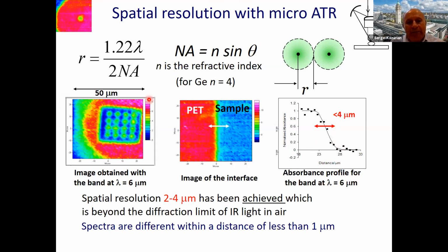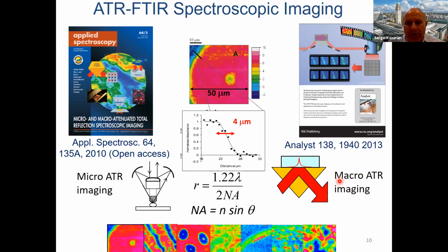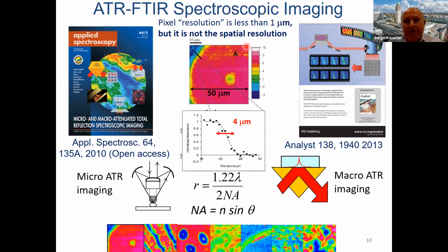And if we divide this area 50 micrometer by 50 micrometer, 50 by 64, actually spectra are different within less than a micrometer. But strictly, spatial resolution would be 4 micrometer for this wavelength in the fingerprint region. And this slide basically reinforces the same idea, and provides you some articles where we reviewed the issue of spatial resolution in great detail, because spatial resolution is very often still used as a pixel size. Of course, pixel size is not spatial resolution.